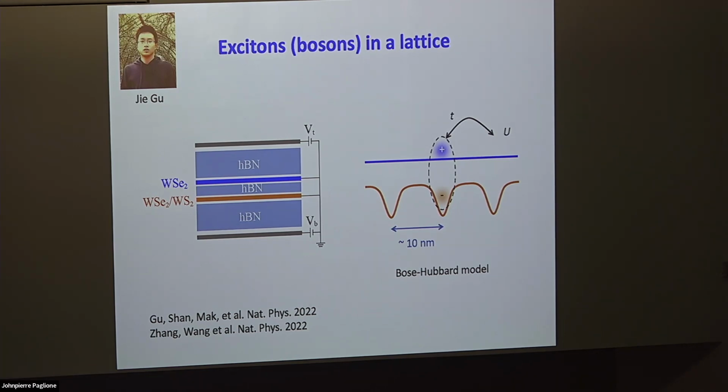Those mini bands come from the band bottom, so think about the extended zone. Right after they open up the gap, they still retain the original orbital character. They will go to the moiré potential minimum, whichever site, AA or AB, gives you the moiré potential minimum. I think it's the AB. Then the electrons are localized at that location. And this spin is the real spin of the electrons.